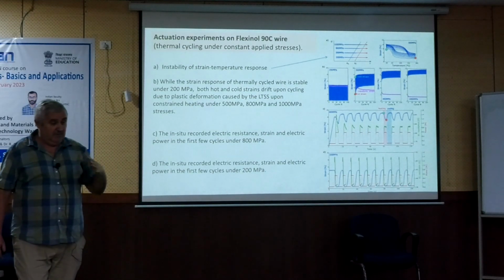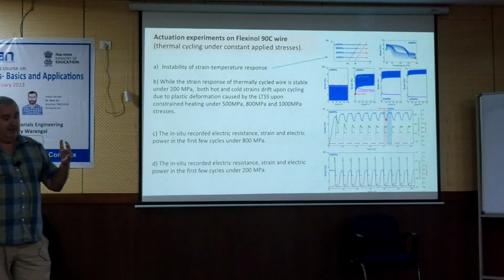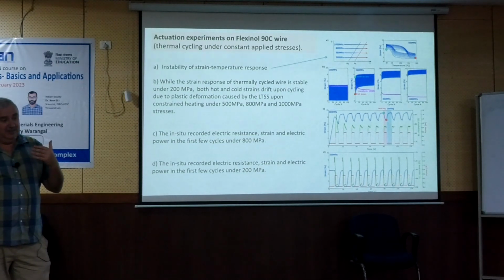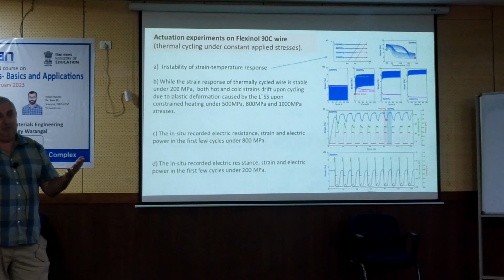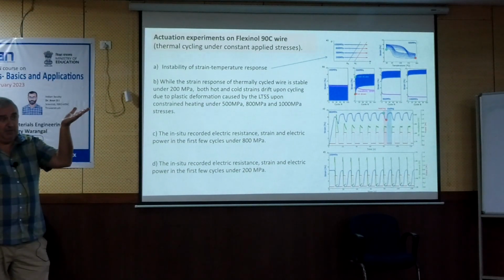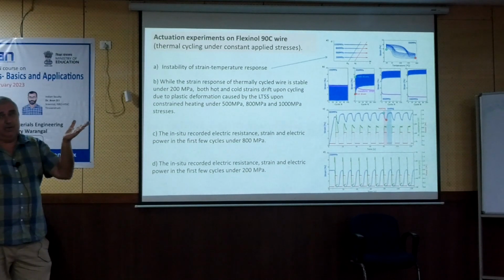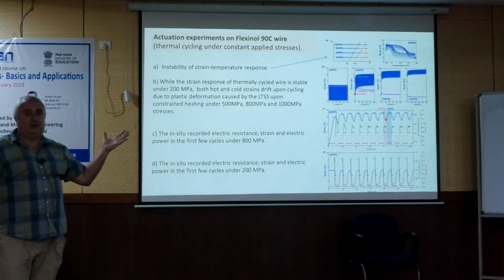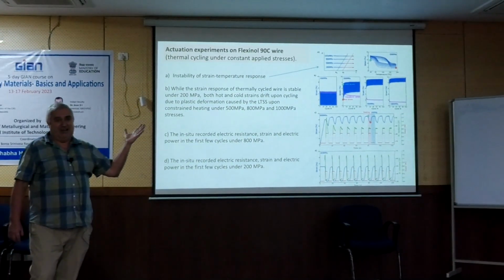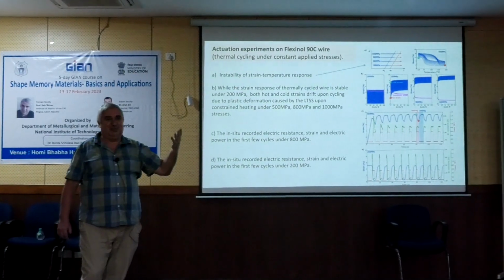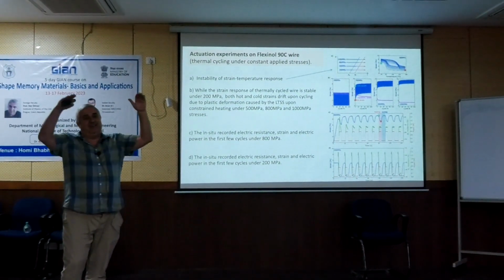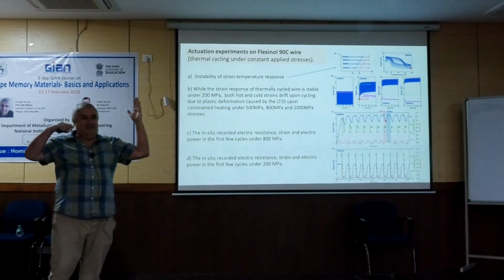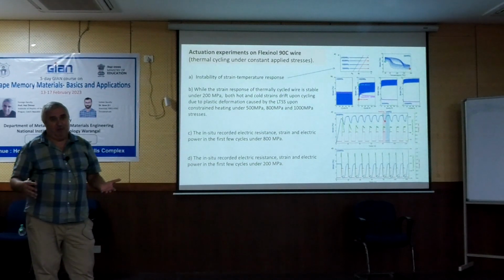In the last 10 years, everywhere, Japan, Europe, US, India as well, people have been working on developing alloys which can be used at 200 or 300 or 500 Celsius. So it means, first of all, shifting the AF temperature to higher temperatures, but at the same time, and equally important, preventing dislocations from gliding in this material. I like these kinks, but in order to have a functioning high temperature shape memory alloy, the kinking has to be shifted up to 500 Celsius and 500 megapascal. If it's below, we have a problem. So these alloys are somehow strengthened.